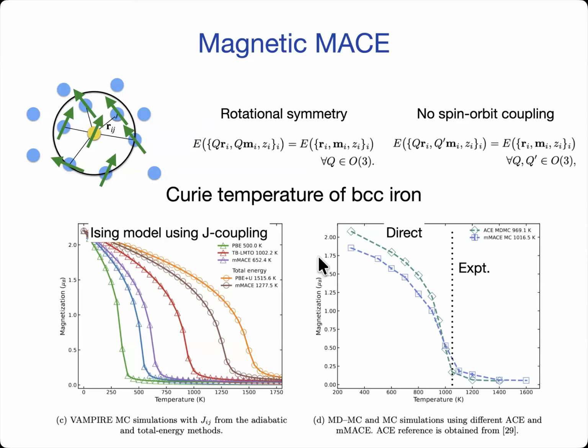Now, this has been studied for a long time with effective models. So on the left, I'm showing Ising model simulations where the J couplings between the neighboring spins is extracted from density functional theory using various ways. And of course, all of them tell you that this is a ferromagnet with a Curie temperature, but it's not very predictive. You can see that depending on how you extract those J couplings, and this is not just nearest neighbor, but a few hops away, you get completely different Curie temperatures.